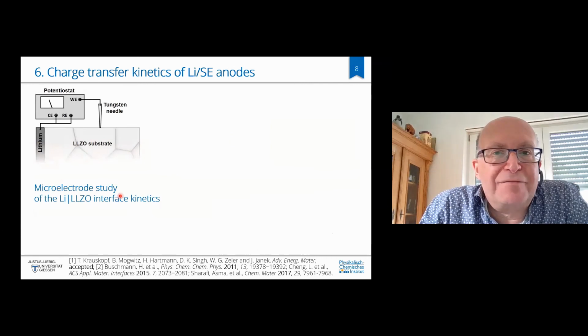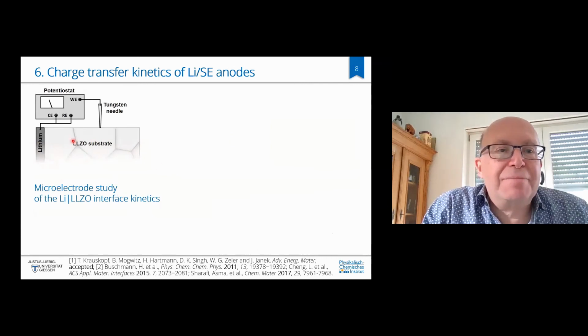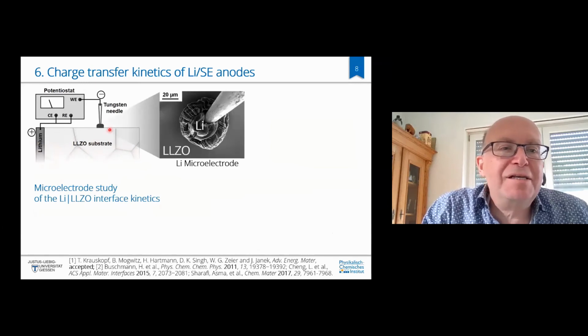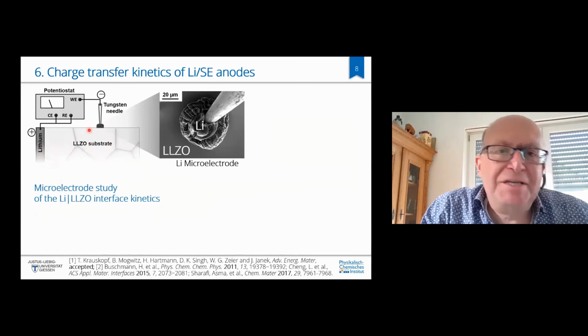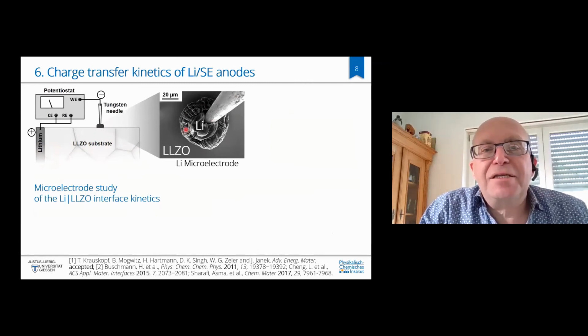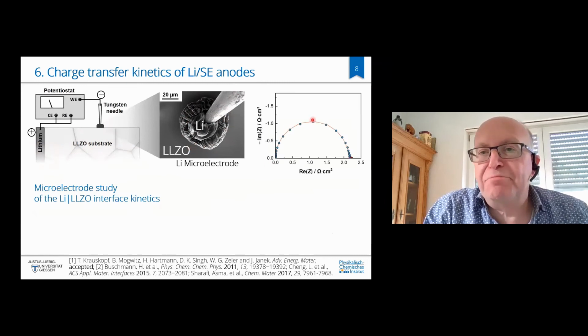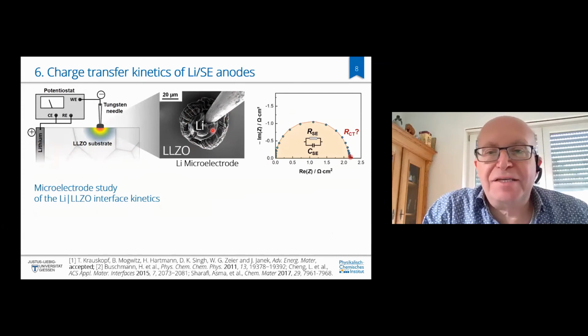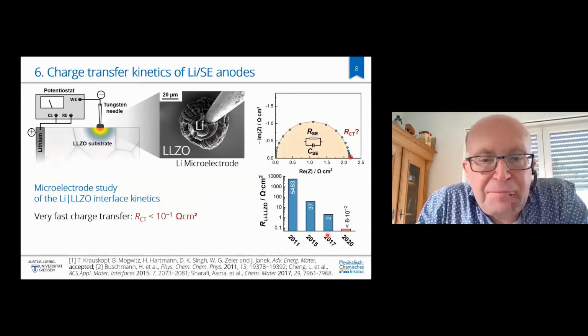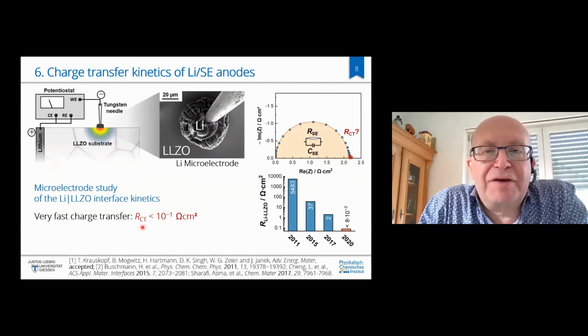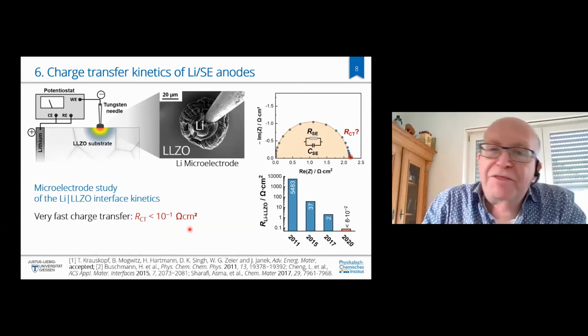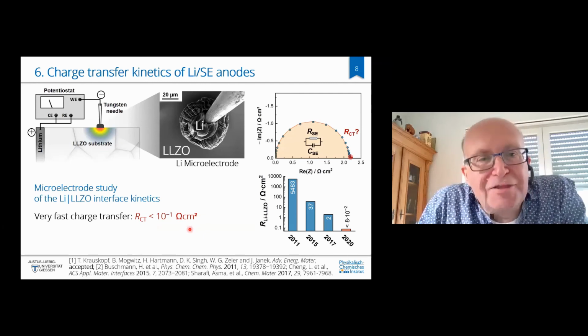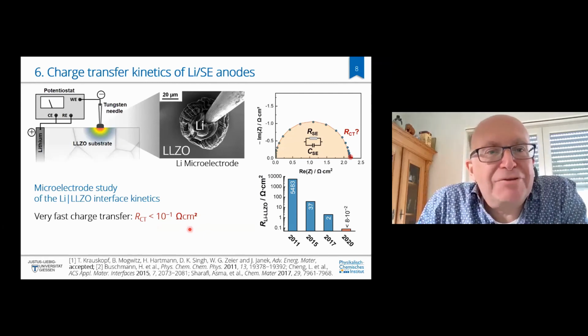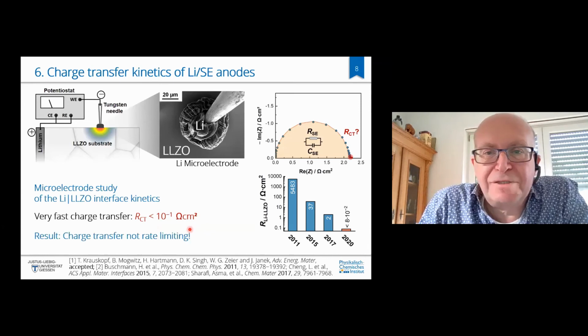And I think, Tom, this is the final experimental slide to be shown, is use that to make another very nice experiment on a single crystalline grain of LLZO in a very, very clean environment. He used a tungsten needle, deposited some lithium before, and then measured the impedance of this single contact. And the result, in fact, is that the areal resistance or the charge transfer resistance of an ultra clean metal solid electrolyte contact is smaller than 0.1 ohm square centimeter. So I think this is exciting on the one hand, because it shows that the electrode as such, the metal transfer, the charge transfer is not limiting. It's the morphological development of these electrodes that is limiting.